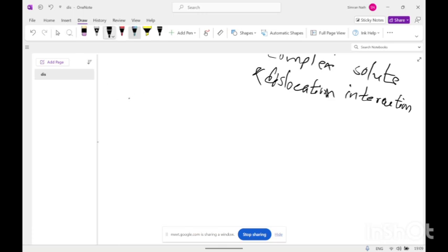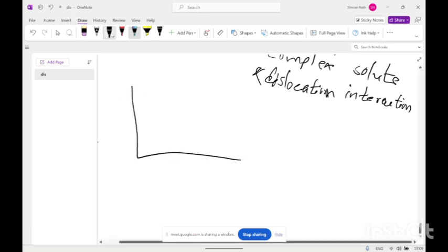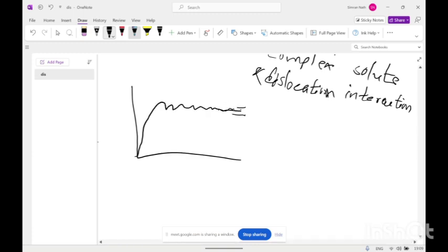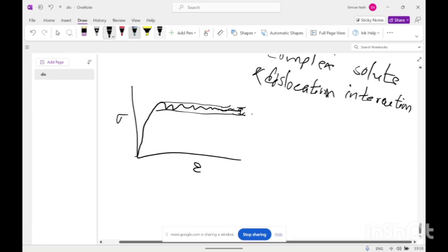Next is the magnitude of the serrated flow. So this means there is a range of decreasing and increasing stress with increasing strain. This amplitude, defined as delta sigma, increases with increasing temperature. So delta sigma increases with increasing temperature.